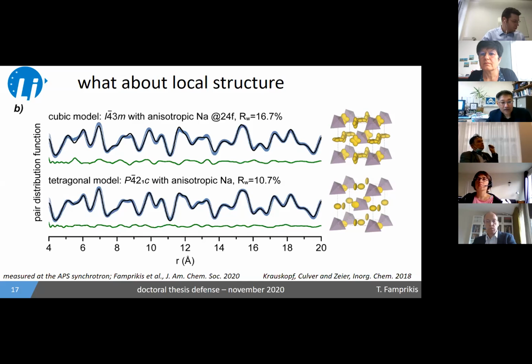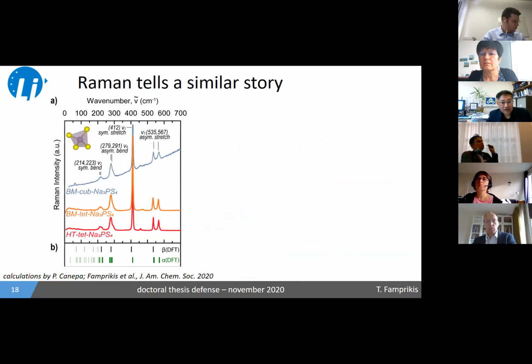We went further to characterize the local structure by Raman spectroscopy. So you can see here the Raman spectra of the 3 Na3PS4 samples. From a first look, they're quite similar. The peaks that you see are more or less the same. Basically, the spectra are dominated by the normal modes of the PS4 tetrahedron, noted here as ν1 to ν4, asymmetric and symmetric bending and stretching. So then the question was, okay, would we see a difference if the ball mill sample in blue was actually cubic? So we performed some group theory analysis and some DFT calculations, which you can see down here.